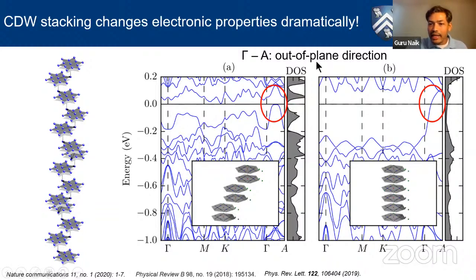On the other hand, if the stacking were all on top of each other, then we can have the density of states non-zero at the Fermi level. Which means it's metallic. So this paper suggested that just by changing the stacking of the CDW domains, the material can exhibit semiconducting or metallic electronic properties in the C-axis. So we thought maybe that's what is changing the optical properties.